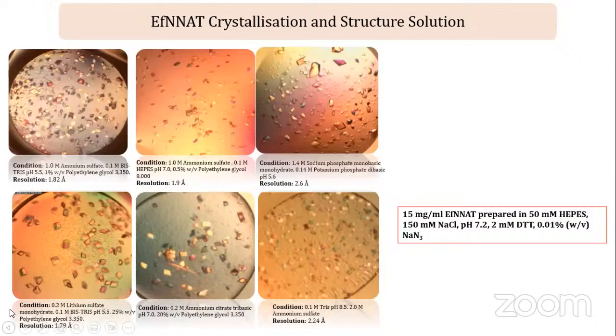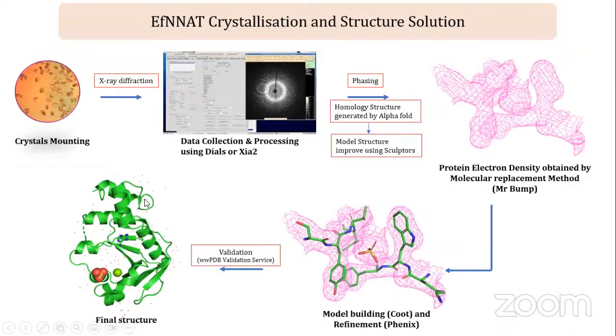these are pictures of some of the crystals we were able to get from this same protein at various conditions. These crystals all diffracted at a very good resolution, ranging from 1.79 to about 2.5 angstroms. Upon getting these crystals, what we did next was to subject them to X-ray diffraction, and this was done at the Diamond Light Source in the UK.